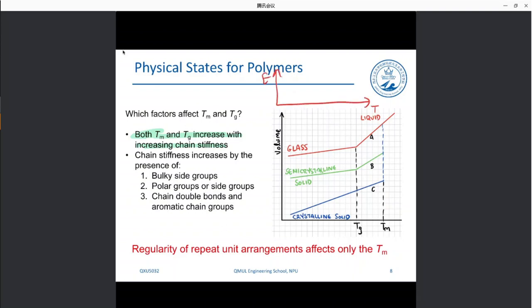of the volume versus temperature, where we have here the glass transition and here we have the melting point. So we need continuous increase of thermal energy, okay? So initially, we need the increase of the thermal energy in order to have the chains start moving, okay? And change their conformations. In that case, we pass through the glass transition, and then we start disentangling our chains. So we have chain slippage, and once we have chain slippage, the chains are able to freely move within the molten polymer. So we have passed through the melting point, okay?